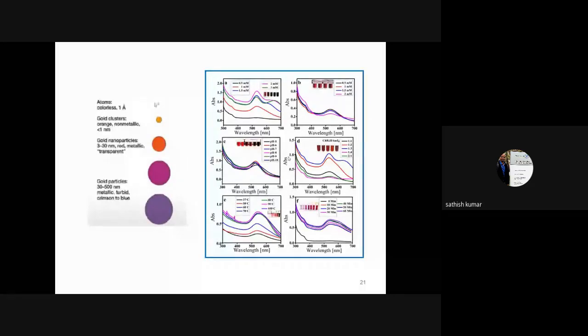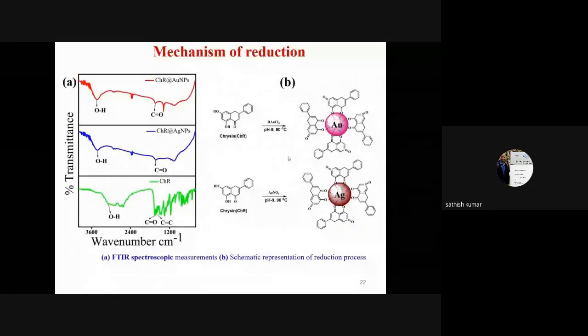So as I mentioned earlier, the size and the shape of the particles largely influence the biological fate of the nanoparticle. So we have to be very careful, and we have to give more concern to the size and the shape of the particle. Apart from the size and shape, another important criterion is the surface chemistry. The surface chemistry and the surface properties of the nanoparticles can be studied through different spectroscopic analysis. The preliminary spectroscopic analysis is usually FTIR analysis. So this will give some important information about the functional group which is involved in the reduction of metal ions.